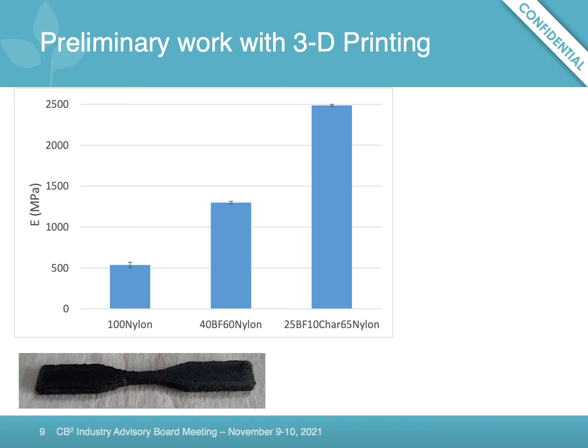And when we conducted some tensile testing in order to evaluate the Young's modulus, what we found was that formulations with basalt fiber included definitely had significantly improved Young's modulus compared to neat polyamide specimens. However, with inclusion of only 10% biochar, the Young's modulus tremendously improved, significantly improved compared to the formulation that included 40% by weight basalt fiber.